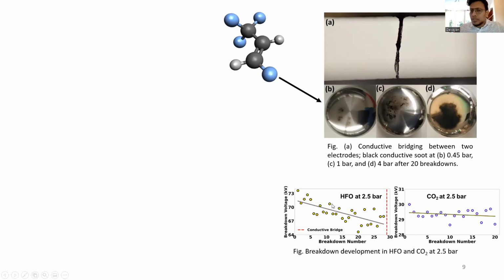So coming into this, the peculiar thing is, let's consider HFO with CO2. If we consider breakdowns in CO2, you see the values are super coherent. It's almost from 28.5 to 30. It's always within the range. But for HFO at similar pressure, what we see is you always have a reducing trend. So it starts off at 73, it goes down to 64 and even lower. And why? It's because of the soot and the decomposition products that you have.